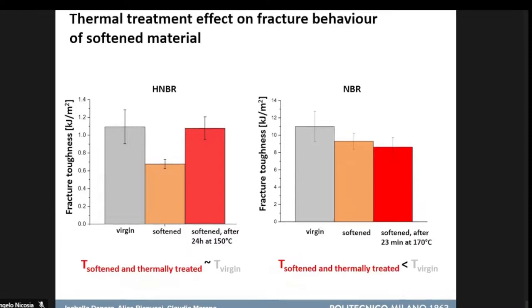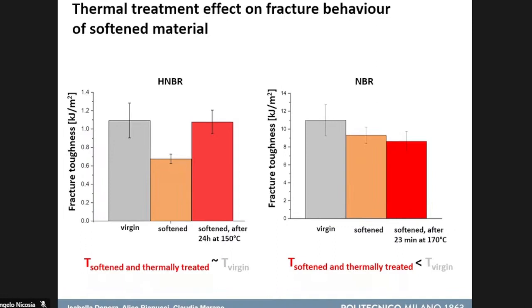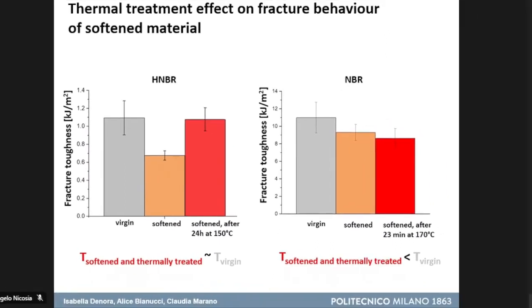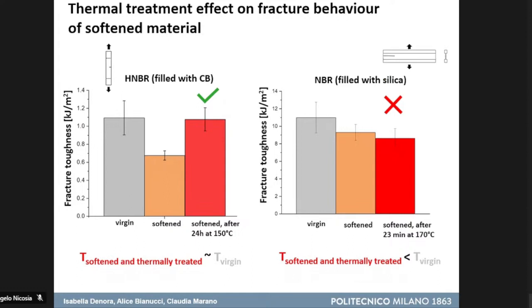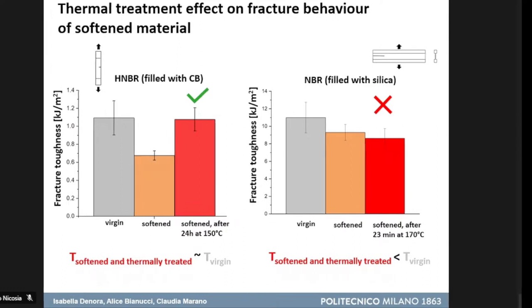So we can see that on the first material, after the thermal treatment, the softened material has a fracture toughness that is comparable with that of the virgin material, while on the other material a different result was obtained because the fracture toughness of the softened material after the thermal treatment is not equal to that of the virgin material. We don't know what is the cause of this difference. We have hypothesized that it was due to the fact that recovery was checked on just uniaxial tensile loading conditions, while the fracture test in this case was performed with the same loading conditions, while in this case with a different condition, because this is pure shear loading conditions. Or maybe also the fact that the material is different both in matrix and in filler.